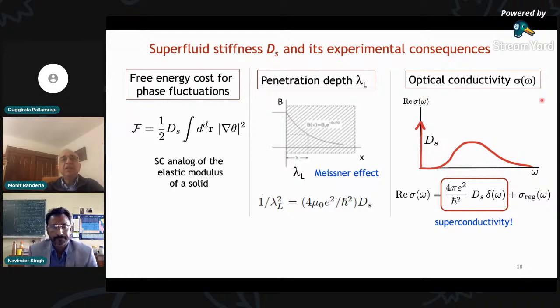If I look at the optical conductivity, which by that I simply mean the real part of the frequency-dependent conductivity, the one that leads to absorption of energy. Then in a superconductor, actually there's an energy gap. So there is no absorption at low energies. And then, of course, there's some absorption, and it could be much more complicated than what I've shown you. But because it's a superconductor, the DC conductivity must be infinite. And that DC conductivity actually is a delta function.